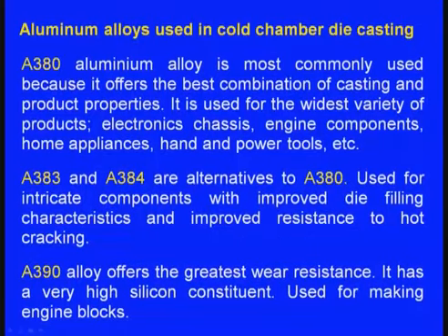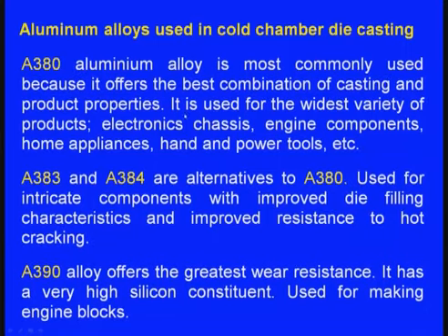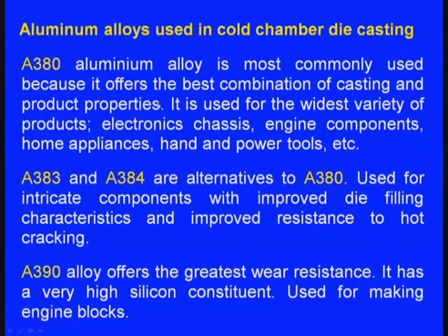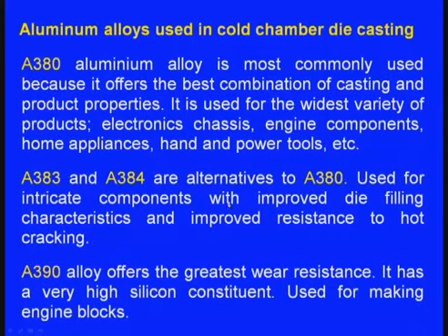A380 aluminum alloy is most commonly used because it offers the best combination of casting and product properties. It is used for the widest variety of products — electronics chassis, engine components, home appliances, hand and power tools, and so on. A383 and A384 are alternatives to A380, used for intricate components with improved die filling characteristics and improved resistance to hot cracking.